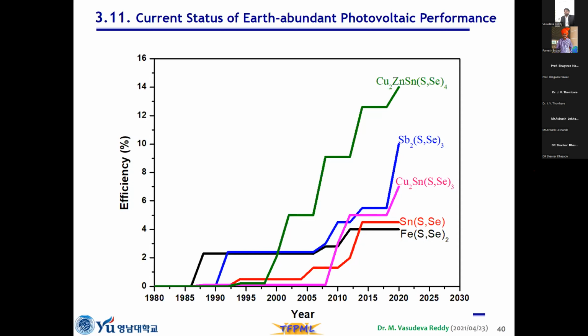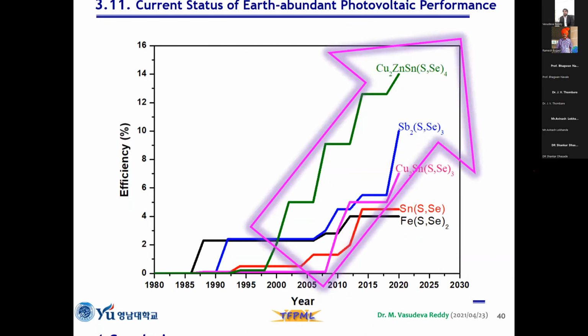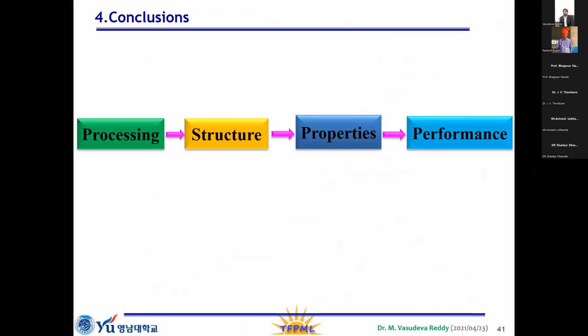The suitable process is the two-stage process. It consumes less energy and gives good grain growth for solar cell application. However, the drawback of these materials is that the efficiency is still lower compared to CIGS, silicon, and perovskite solar cells. Almost all these solar cells have reached around 25 to 30%. But these new materials are still struggling to overcome 15% efficiency. But we can improve the efficiency, as shown here, by optimizing the process parameters, and we can control the structure, and as a result we can also control the properties, and we can achieve reasonable performance.